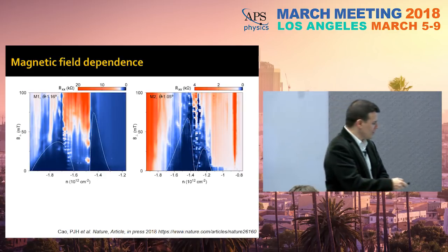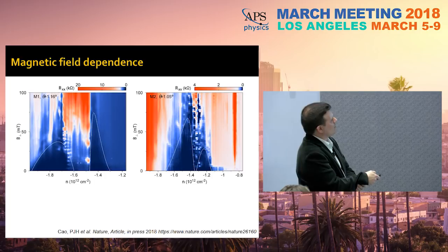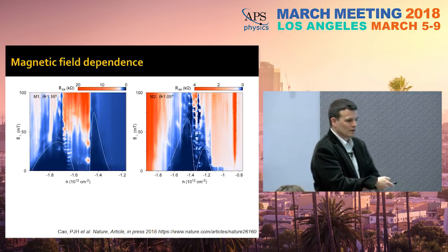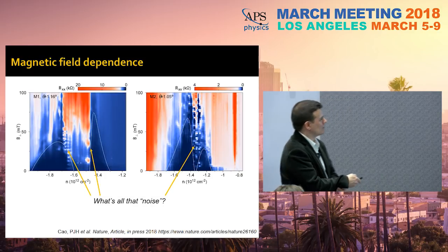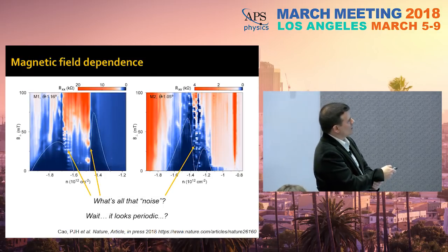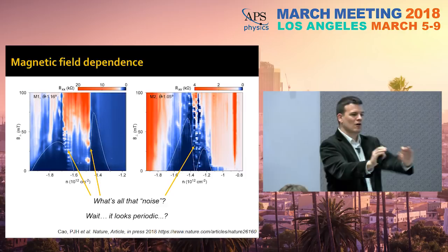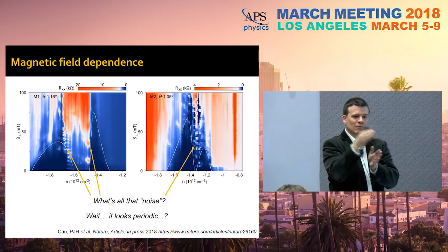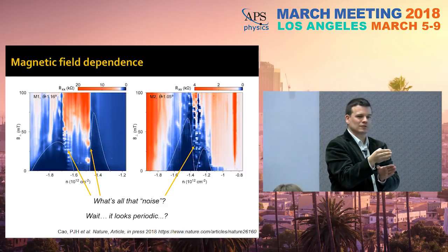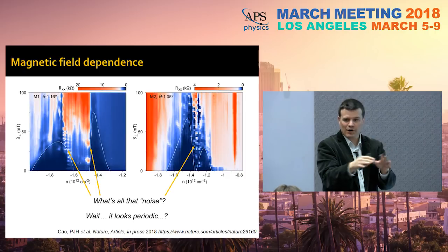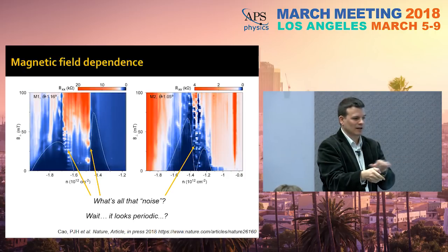Now, when my students showed me this data, I was like, oh, this is nice, but it looks kind of ugly compared to the other domes. What is all this noise? Well, it turns out, actually, this is not noise. What happens is that this thing is actually periodic. If you go at the boundary between the Mott insulator and the superconducting region, your system breaks up into islands which are superconducting and insulating.